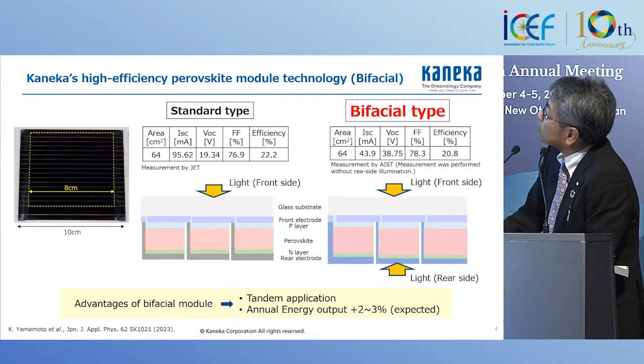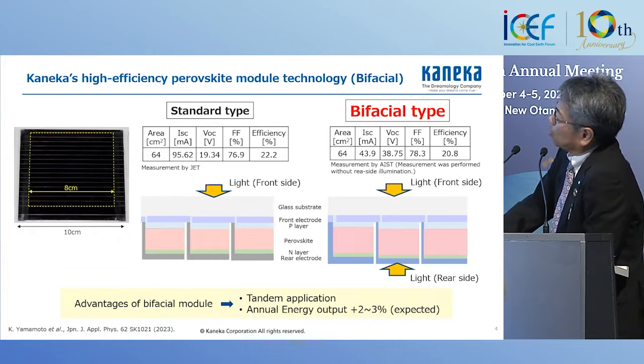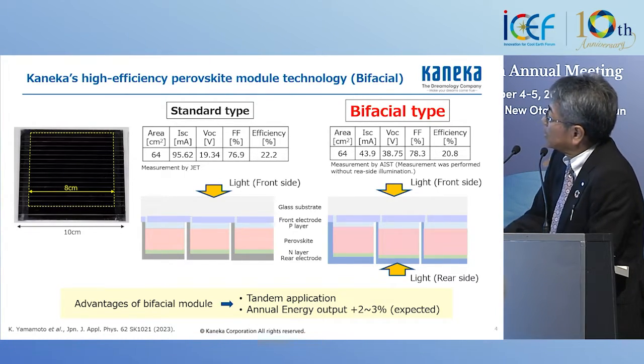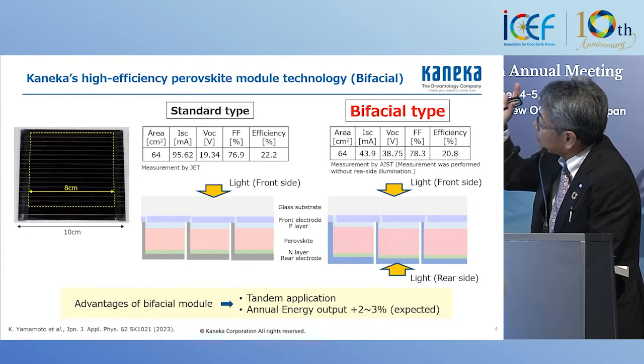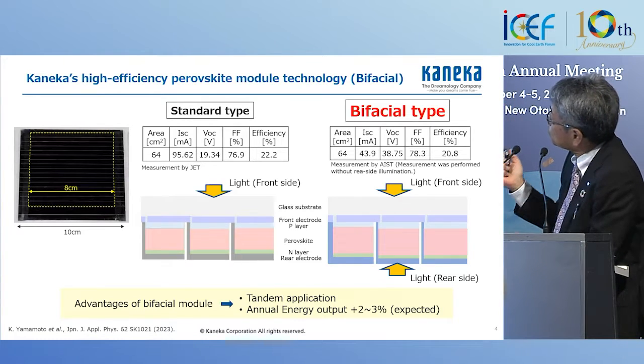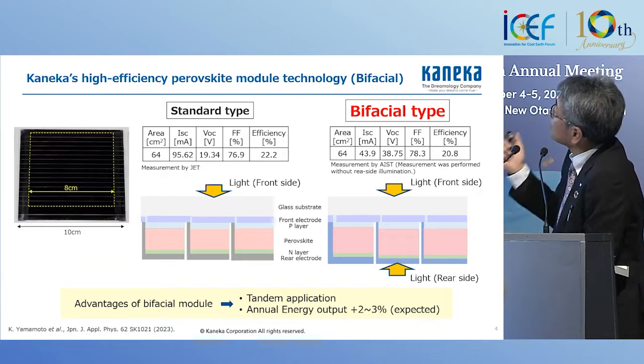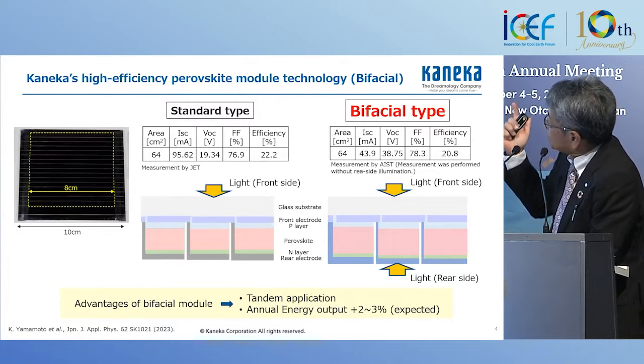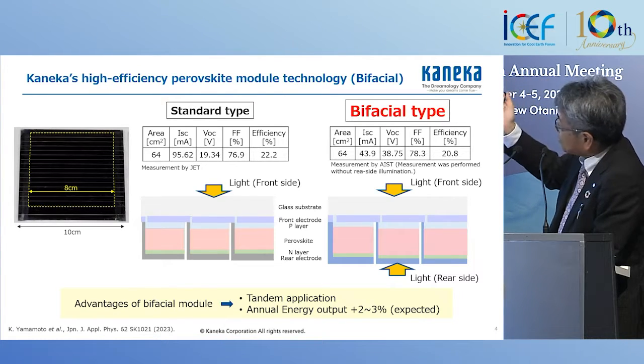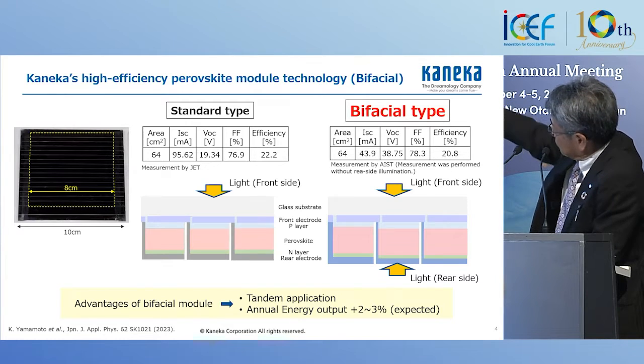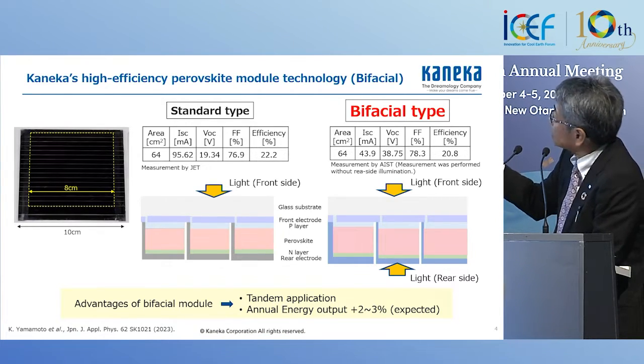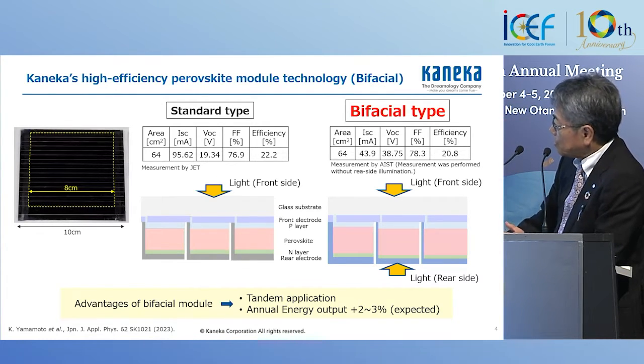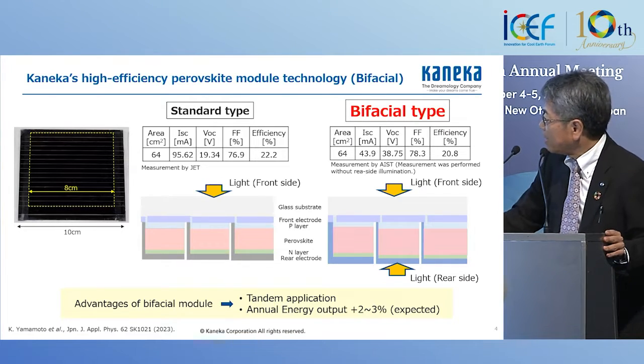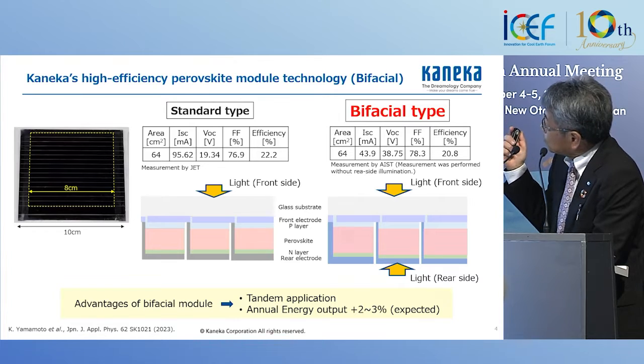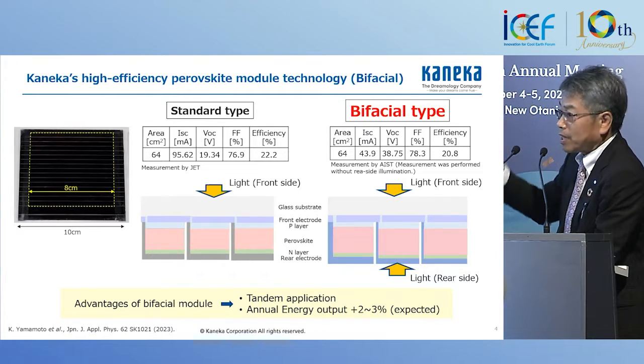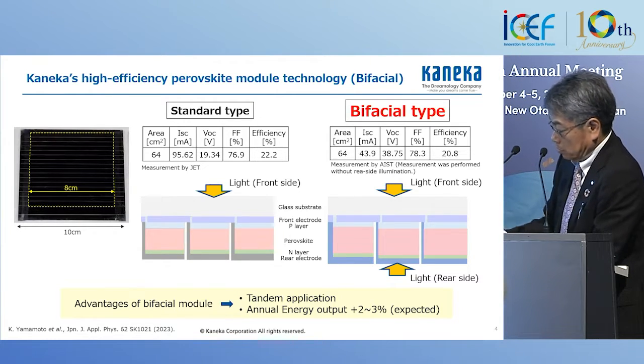This is our mini module result. For the standard type we have shown over 22.2%, with series interconnection, glass, front electrode, P layer, I layer of perovskite, N layer, rear electrode. Now we are very much focused on the bifacial type. We also showed 20.8%. This measurement was also performed by AIST, confirmed, but for the measurement itself, we cannot take into account the light from the rear side. So in a real situation, it depends, but usually up to 2 to 3% higher energy output is expected. It depends on the installation situation, but usually bifacial 20.8% is higher than that of 22.2% from an energy point of view.